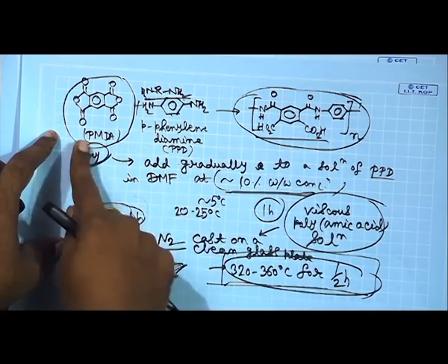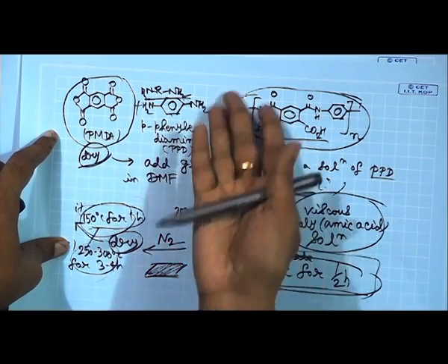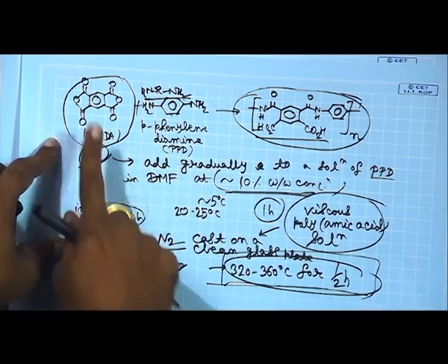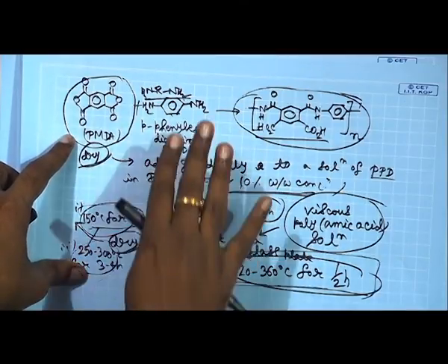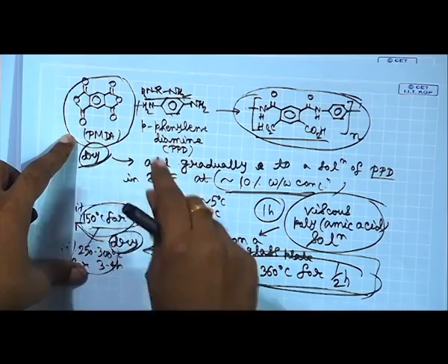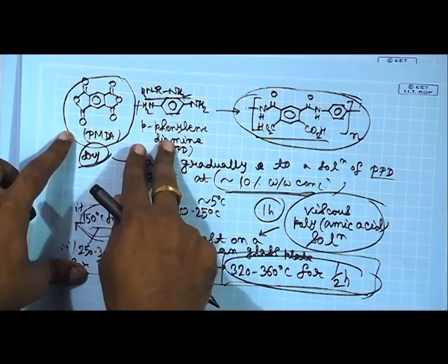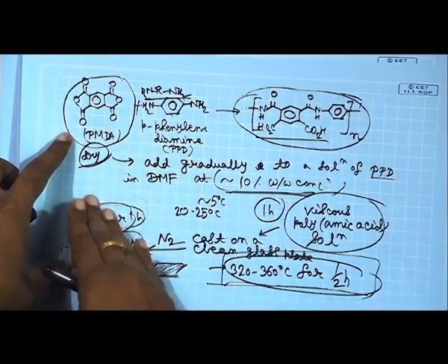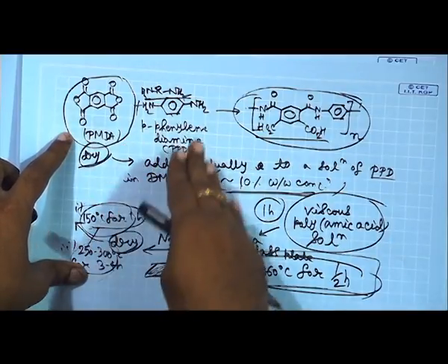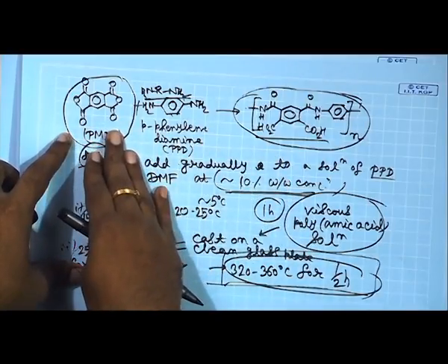Second thing is that the solid dianhydride that you are adding gradually, you are using, say, dimethyl formamide, DMF, as a solvent. This solid does not dissolve immediately in the solvent. So, what can happen is that the rate of dissolution can be slower than the rate of polymerization. It can gradually, slowly dissolve, but the rate of polymerization may be faster than the rate of dissolution, and we know if we have several rates involved, the rate determining step is basically the slowest step.